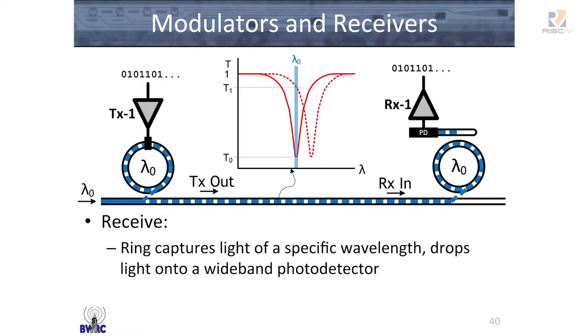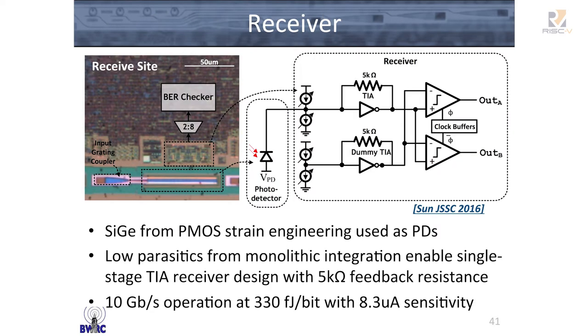For the receiver side, we also place a micro-ring resonator. For wavelengths resonant at the receiving ring's resonant wavelength, it picks up the light and drops it off into a drop-port photodetector. We build the photodetector by leveraging the existing silicon germanium in the process — silicon doesn't absorb infrared light at these wavelengths, but germanium does. Silicon germanium is a common material in modern processes used to strain PMOS transistors, so we leverage that layer as an absorption material for our photodetectors. Using on-chip circuits, we build receivers with good sensitivity at tens of gigabits per second per channel.